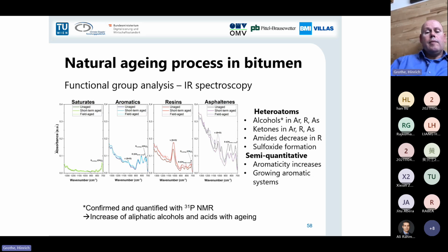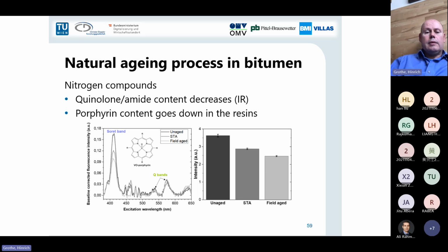And we can see changes in alcohols in aromatic systems and in aliphatic systems. And we can observe the ketones and the amide bands. And we see an increase of the aromaticity. And as I said already, that's a little bit in contradiction to what we saw on the NMR. But it's interesting, and I will later on come back to that.